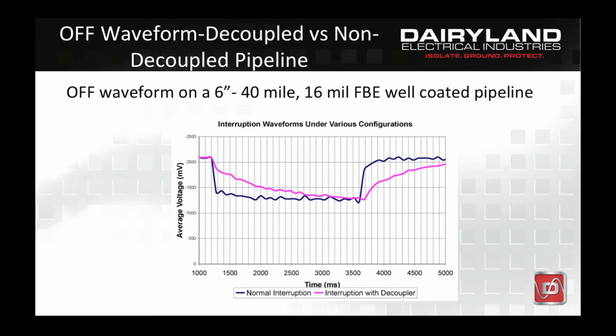It is only if the potential were not at least minus 0.85 volts that additional testing by other means would be required to determine if the pipeline were adequately protected. While such long on and off times would greatly slow down the process of taking a close interval survey, it is an option to consider.